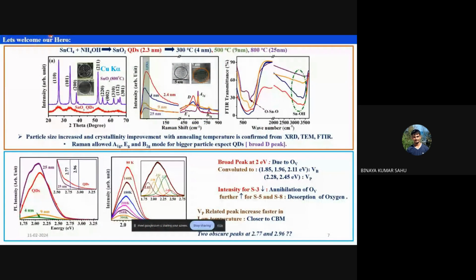So let's welcome our hero to the movie. As I told, this is tin oxide, and we didn't go for a very complicated and costly technique. We took a very simple chemical route. We basically added ammonium hydroxide to stannic chloride, and what we obtained is the tin oxide quantum dot. Why am I telling this quantum dot again? Because the size is 2.3 nanometer. As I was telling in the introductory part, if it is less than 2.7 nanometer, then it can act as a quantum dot.